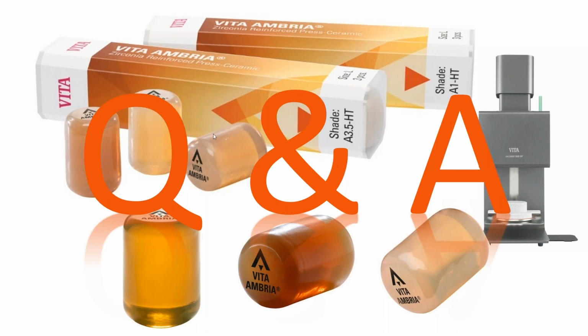All right, we have another one: I get fins sometimes after I press. We kind of went over that when talking about fins, where you're seeing a lot of penetration of your pressed material beyond the contour of your wax-up. That could be a couple things. It could be the microfracturing of your investment because you put it into your burnout furnace where the ring is too cold.